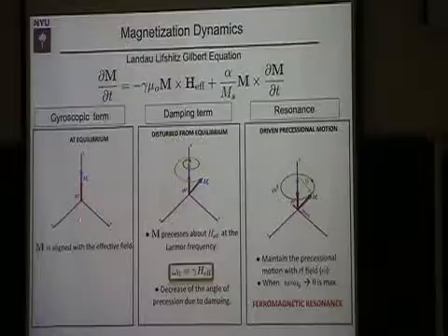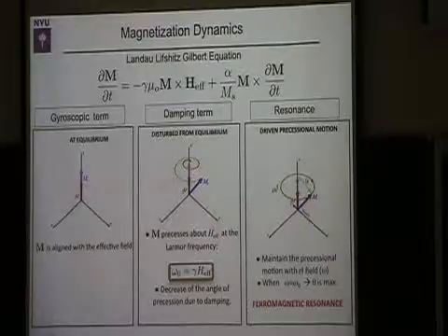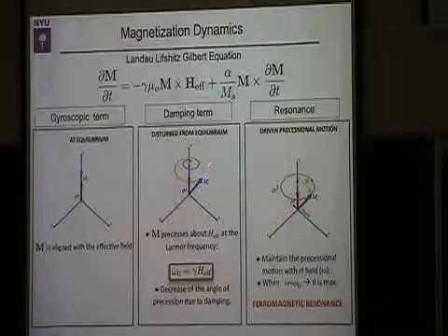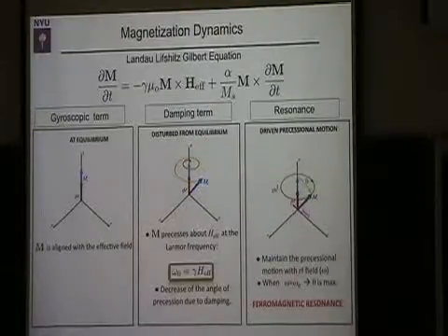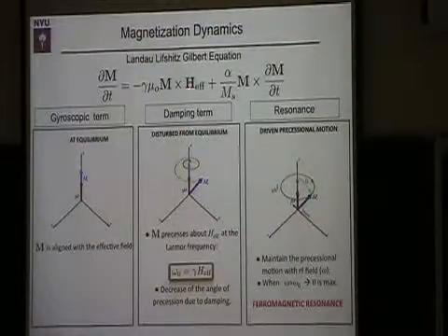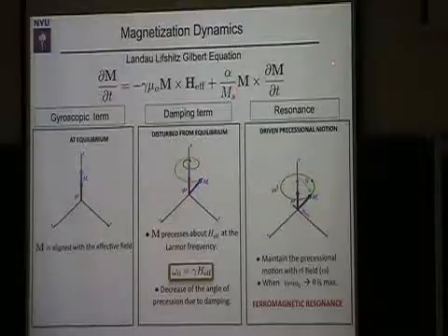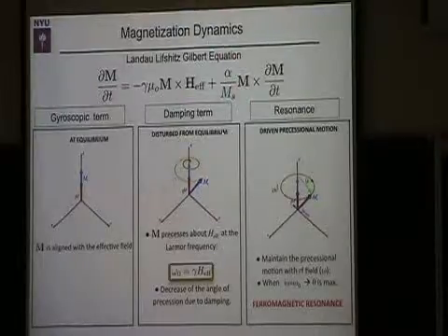Well, if you're in equilibrium, the magnetization is along the effective field, and you keep pointing that direction. If you're away from equilibrium, you precess. But this alpha term, alpha times dM/dt, causes the precession to relax toward the equilibrium direction. So that's the simplest model. This is a phenomenological model. Up to here, you can understand this as resulting from the equations of motion. This is just putting in what you can imagine will cause dissipation.